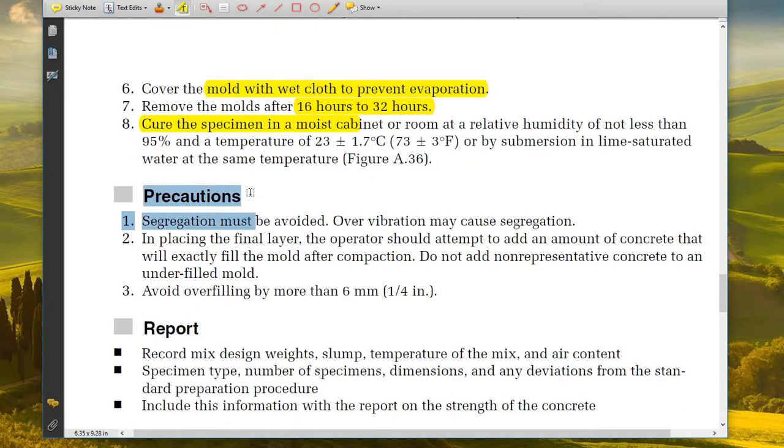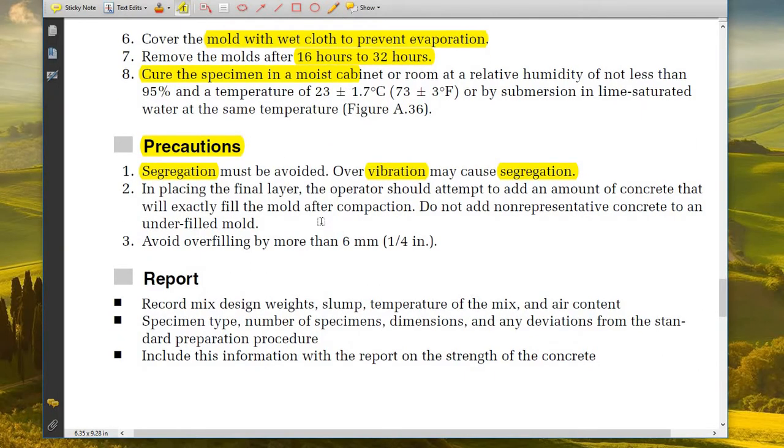We need some precautions. Segregation must be avoided. Over-vibration may cause segregation, so take care with your vibrator. When placing the final layer, the operator should attempt to add an amount of concrete that will exactly fill the mold after compaction.